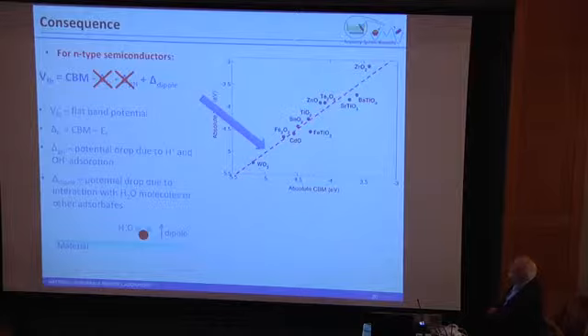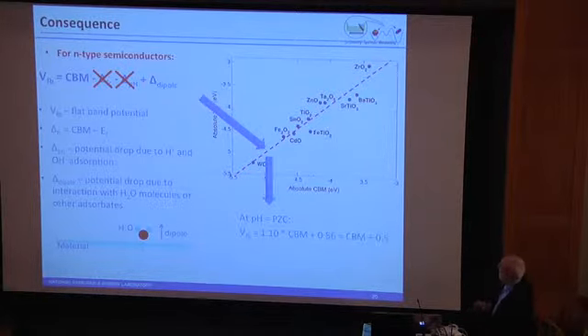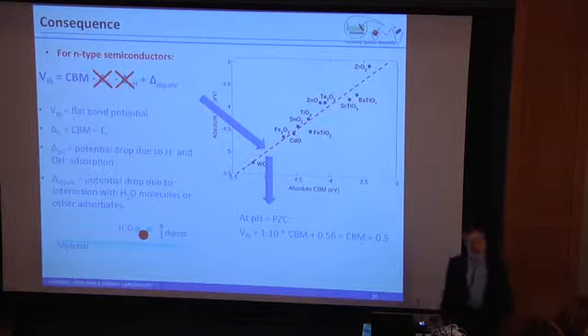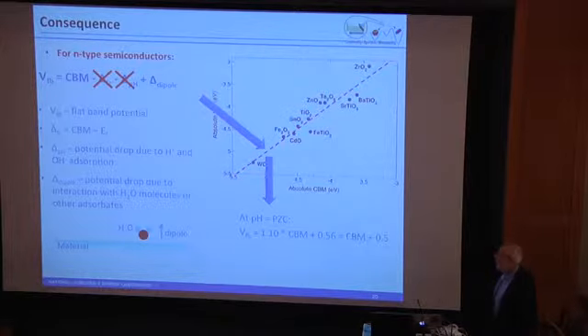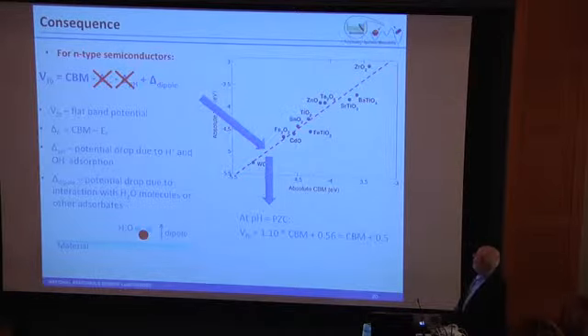And we find something very interesting in the old data, which I will show you seems to be true even in the new data. We don't understand it, but it's actually quite useful, which is that at the point of zero charge, the dipole contribution is essentially 0.5 volts for everything, even non-oxides. So I don't know quite why that is. I would expect that the water dipole would have a slightly different structure, but it appears to have almost identical structure for a whole range of materials, and I'll show you that in just a second.